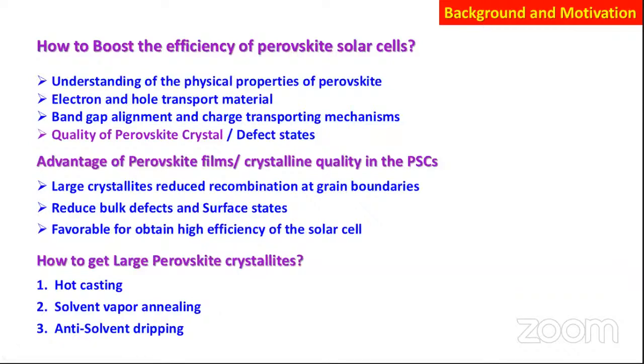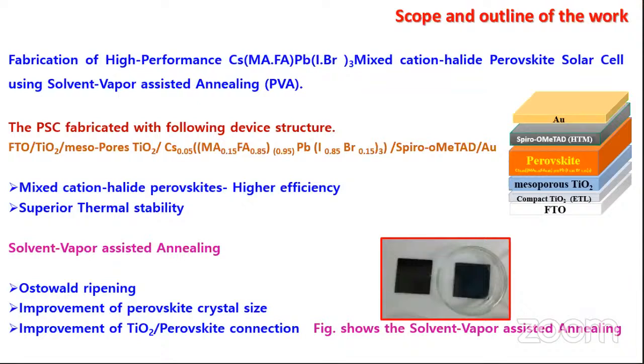My work focuses on fabrication of high performance cesium based mixed cation halide perovskite solar cells using the solvent vapor annealing method. Here I fabricated the solar cell with the following structure. The TiO2 and the mesoporous TiO2 are used as the electron transfer layer. The cesium MAFA Pb halide is used as the light absorber, and the molar ratio of the perovskite was optimized, and this one gives higher efficiency as well as very good thermal stability.